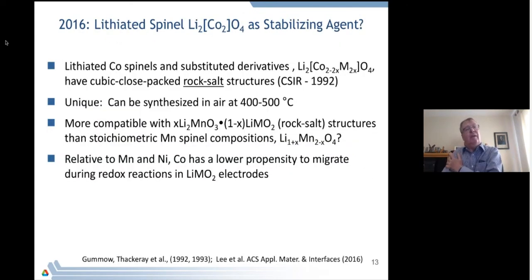So I just want to end off with some comments as to where we are now with work on spinel-related materials. And instead of using manganese spinels as a stabilizing agent, we're looking at lithiated spinels now, because there's this whole family of lithiated cobalt spinels that are fairly unique because they can be synthesized in air at 400 to 500 degrees C, unlike many of the other lithiated spinels, such as the manganese systems, and of course the lithiated nickel spinel has not yet been made at all, chemically or electrochemically. But a lithiated spinel has a rock-salt structure, as do these composite Li2MnO3.LiMO2 structures. So it seems as though it might be more worthwhile and more compatible to use a lithiated spinel rather than a stoichiometric spinel, which has got lithium in the tetrahedral sites.